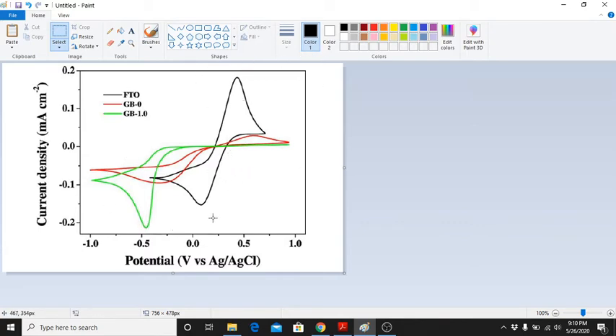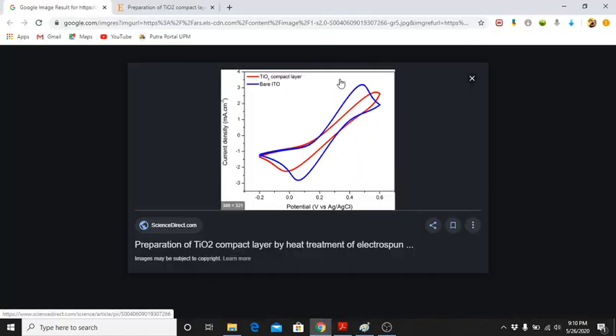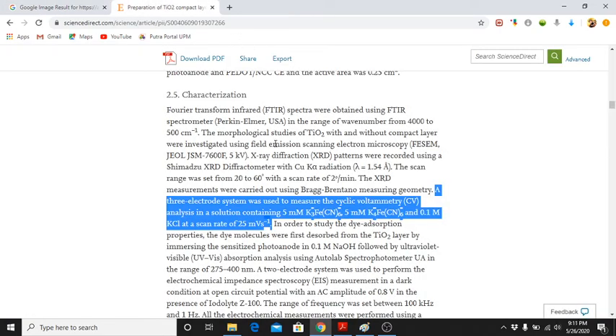However, for the reduction part, we want the reduction to occur. Why? Because when you look at the process of DSSC, the electron flows, right? When the photon strikes, the dye molecule is excited and the electron moves from one TiO2 to another and goes to the counter electrode via the external circuit. So the electron must be accepted at the FTO or TCO, transparent conductive oxide. That's why the reduction must occur. It must accept the electron for the electron to transfer to the counter electrode and back to the dye to complete the cycle. That's why we just focus on the oxidation peak. So it's quite simple actually. For this one also, we focus on the anodic part for the oxidation. That's why one of the important parameters when you are studying the recombination effect is cyclic voltammetry.